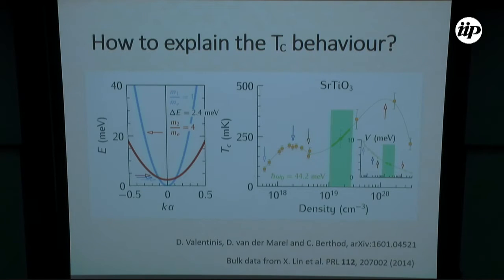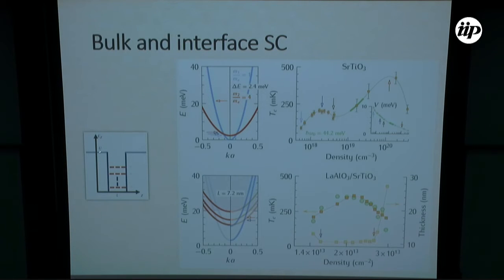So taking this value from the bulk, what they calculated is the superconducting state for a system that is confined in a quantum well with a square potential. And as soon as you confine into a finite size square potential, what you get is a subband structure of your electronic structure, and these will induce shape resonances. And what they see is that if we take into account the carrier density and the thickness, the calculation points, the ones in green, can match quite well our experimental points, the yellow ones. And so taking into account both these parameters, the thickness and the two-dimensional carrier density, we can then explain the behavior of the phase diagram that we observe by field effect.